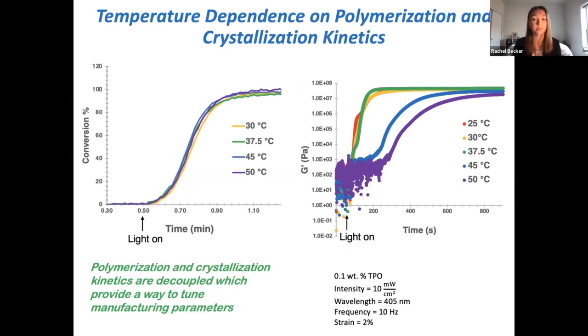And on the right here, we have rheology data, storage modulus plotted versus time of 5 different temperature samples. And we can see that the higher temperature samples of 45 degrees and 50 degrees give us much slower crystallization rate compared to the other 3. So we can conclude that crystallization kinetics are dependent on the temperature at which we polymerize, and we can use both the polymerization and crystallization kinetics to tune our manufacturing parameters.